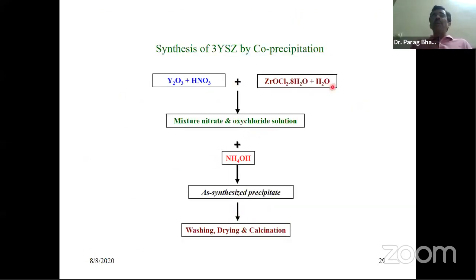The process is simple. This zirconium oxychloride, like I said, comes from beach sand. It is made from that. So we use this chemical, we use yttria, we dissolve it in nitric acid. We have a solution. We add it to ammonium hydroxide. This is called co-precipitation, maybe like simple chemistry. And we get the precipitate. The precipitate is basically zirconium hydroxide with yttrium hydroxide in it. Then we wash it first and dry it. Why do we wash? We want to get rid of chloride, nitrates, everything. Then after drying, when we calcine it, the hydroxide decomposes and gives us the oxide nano powder.